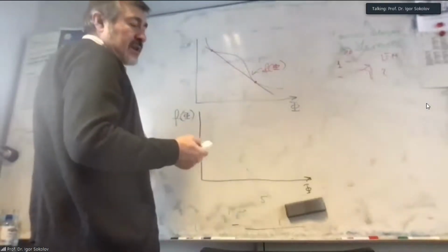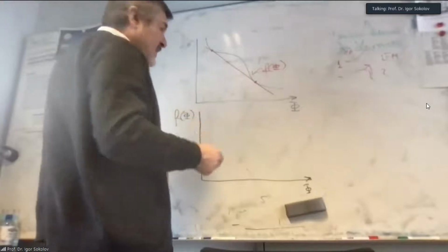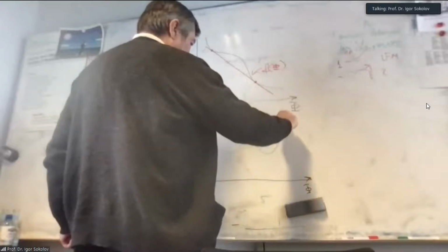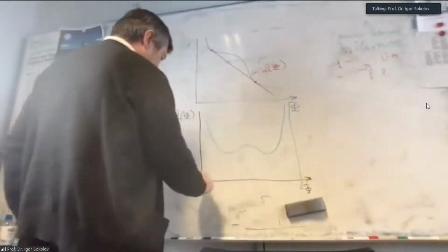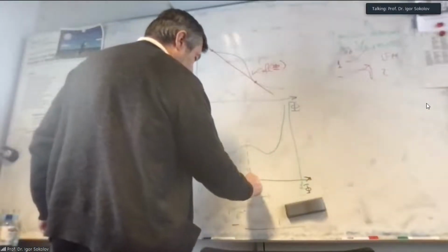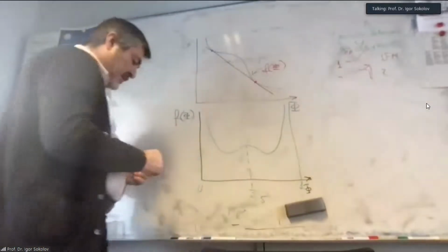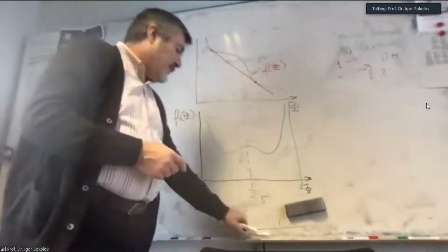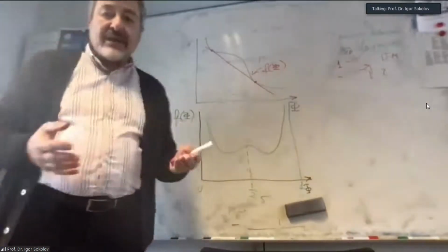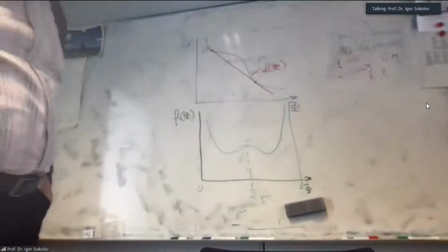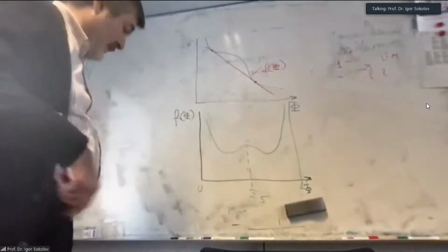But for a symmetric blend, just as for any essentially binary solution of symmetric elements, this f of phi is a symmetric function, because if it has a maximum or a minimum, this is at 1/2, because phi and 1 minus phi simply correspond to renaming of A into B and vice versa.